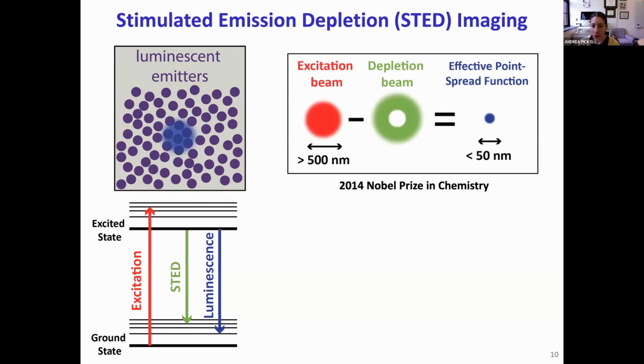But what happens next is that you come in with a second donut-shaped laser beam called the stimulated emission depletion, or STED beam. And the STED beam stimulates emitters within the donut to return to the ground state by emitting a photon. That means only emitters in the central zero intensity region can luminesce, and so that drastically restricts the effective point spread function, typically to tens of nanometers and sometimes even smaller. Super resolution imaging has been very impactful in biology, and for that reason, the 2014 Nobel Prize in chemistry was jointly awarded to STED and another class of super resolution techniques.